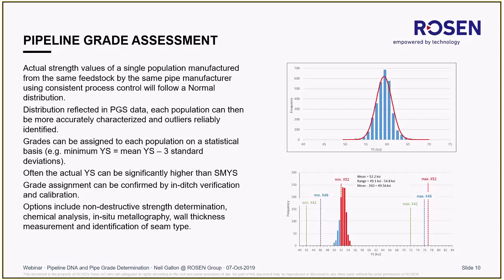This means that not only can we identify the grade, we can also identify the possible minimum strength that you get from that population. Often you'll find that the actual yield strength is significantly higher than the SMYS. On the bottom graph on the right hand side, you can see some distributions with the minimum yield strength for X42, X46 and X52, and the population in there. That population could be X42 or X52 or X46. The actual average yield strength of it would meet X52, but there will be a significant number of pipes below the minimum yield strength of X52. So we would call that probably X46 on the basis that it meets X46 comfortably.